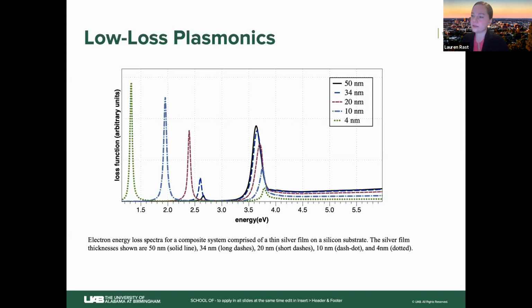So in principle, one way that we can create materials with high Q factors is to mitigate bulk plasmon losses. So really to favor surface plasmon resonances over bulk plasmon resonances. So the surface plasmon resonances, remember, are confined in one dimension, and travel along the two-dimensional surface. So one way to do this is to mitigate losses through fabrication of really, really thin metallic films. In this way, it makes sense, right? Plasmon resonances couple more strongly to the surface plasmon modes. There isn't much bulk there to couple with, right? So we have a higher surface to volume ratio.